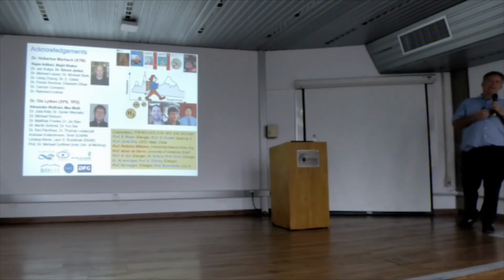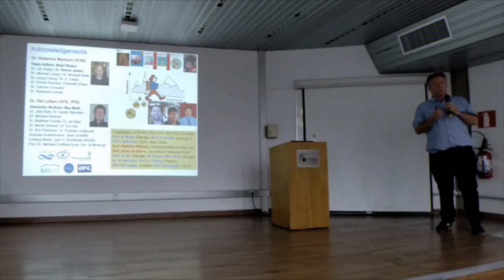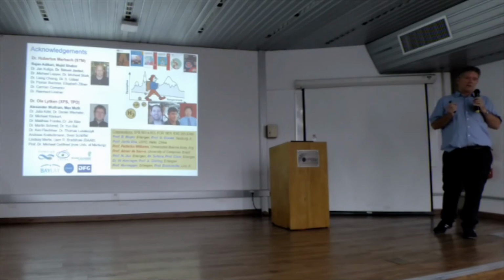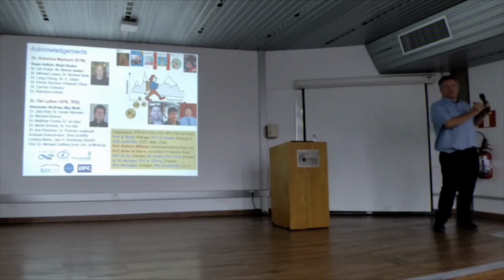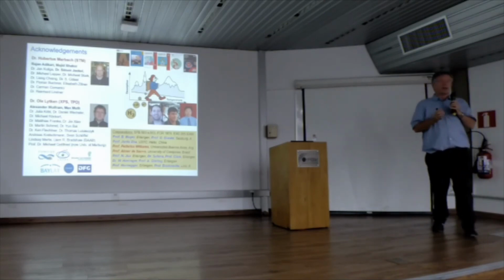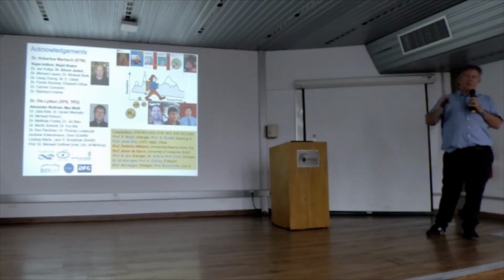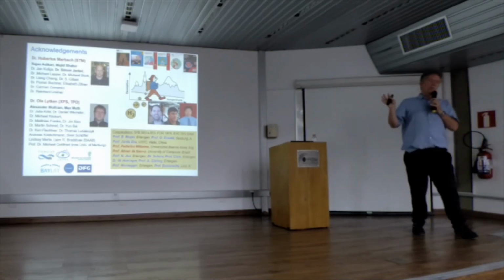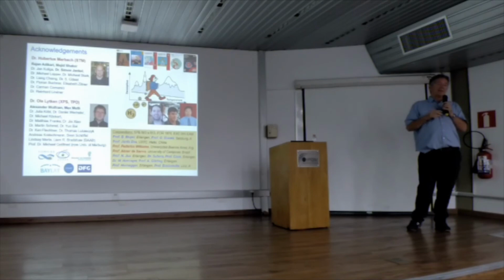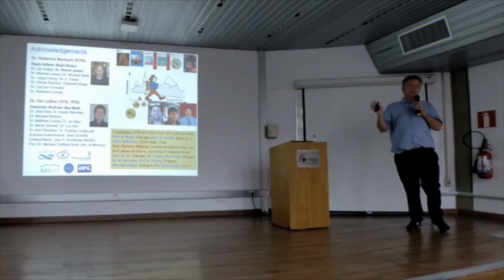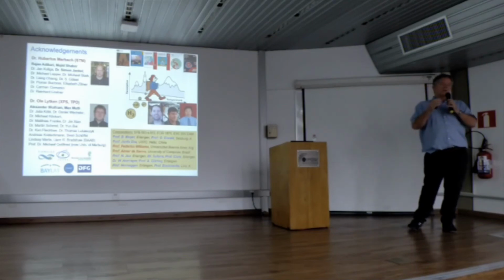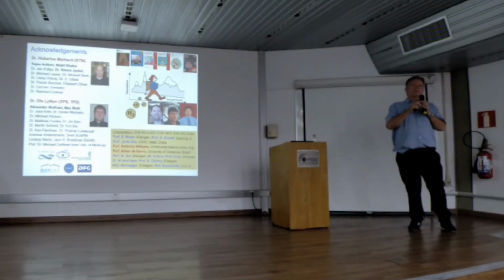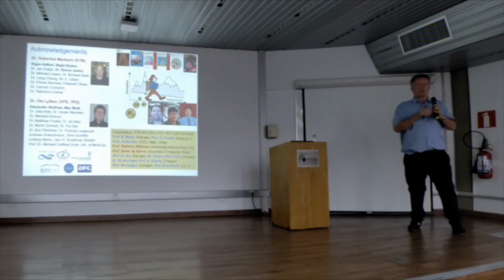And typically the species on surfaces, if they're not charged, because if there's a charge, then it's repelled, then it might be different. But if not charged, they like higher coordination. And if you look at island growth, it typically starts at step edges. Not exclusively, but often at step edges because of this higher coordination, which indicates that the bond at the step edge is stronger than on the terrace. And if the bond is stronger, it doesn't move away.